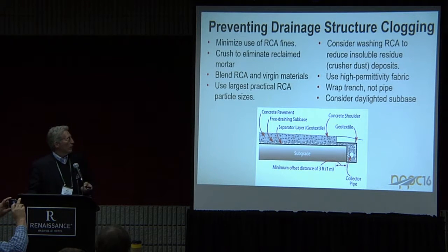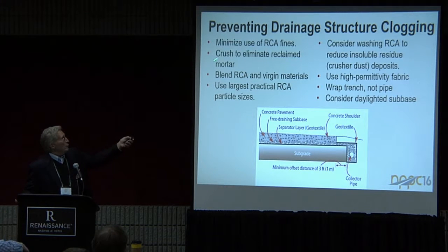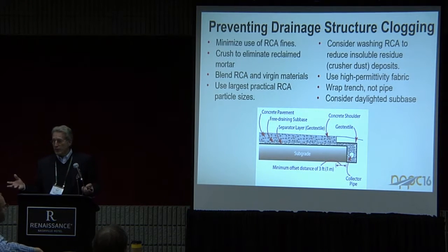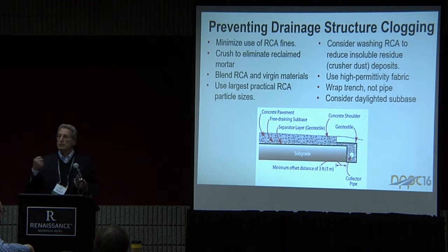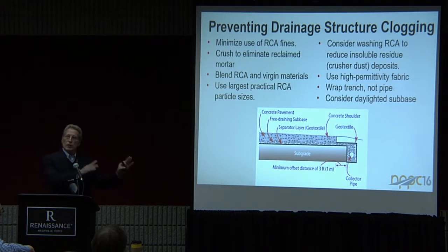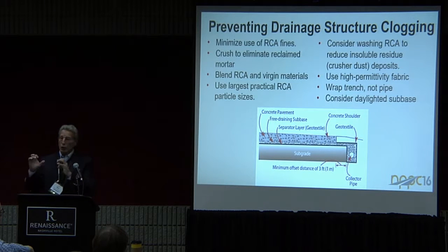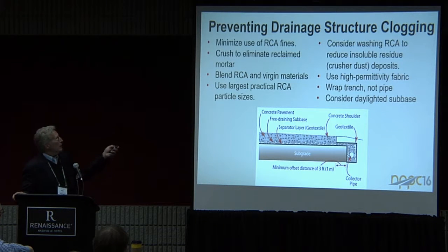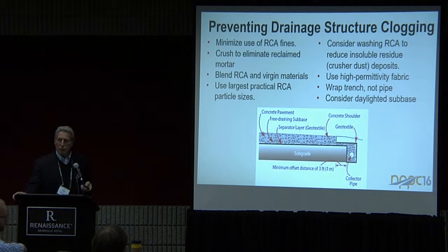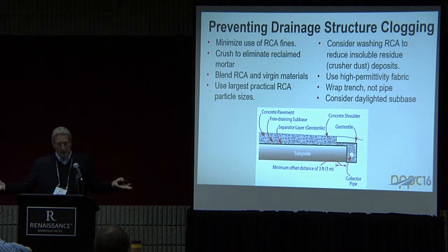Make it a little bit more open graded. Use larger top size aggregate particles. You can even use impact crushing processes to pretty much get rid of the reclaimed cement part. Use those elsewhere and just get back to as close to a natural aggregate condition as you can. Reclaim the original natural aggregate. Blend crushed concrete and virgin materials. Again, large top sizes. Consider washing the material. Yes, it adds another expense, but I have seen some states go to that, washing the crushed concrete.